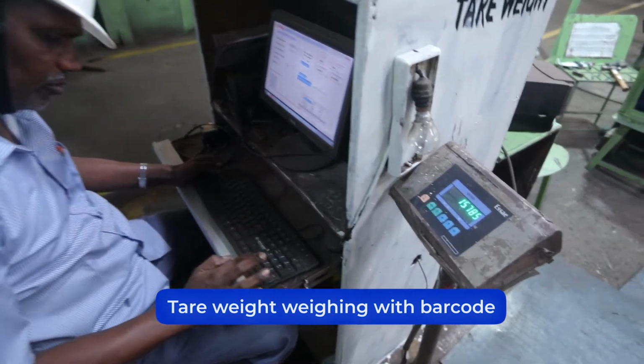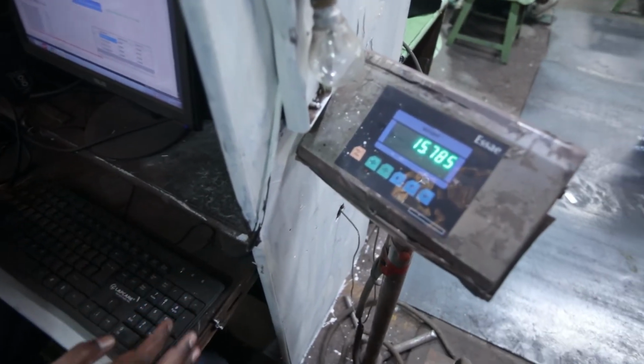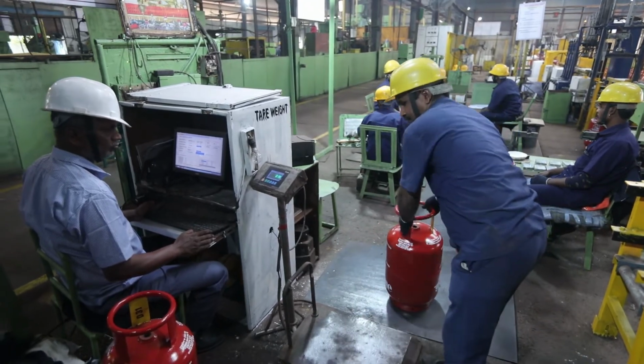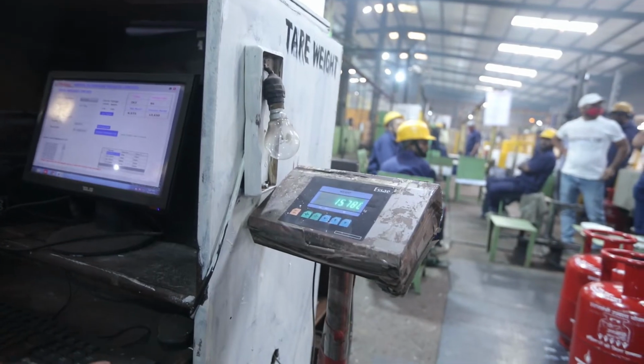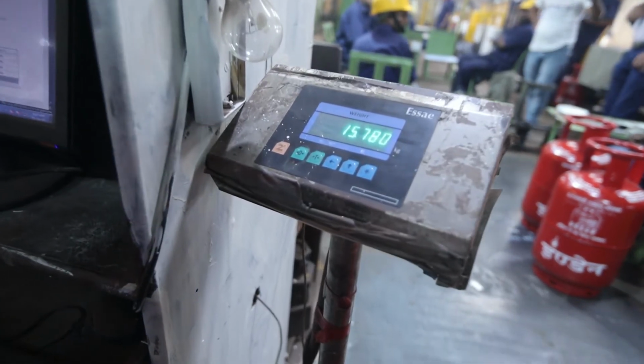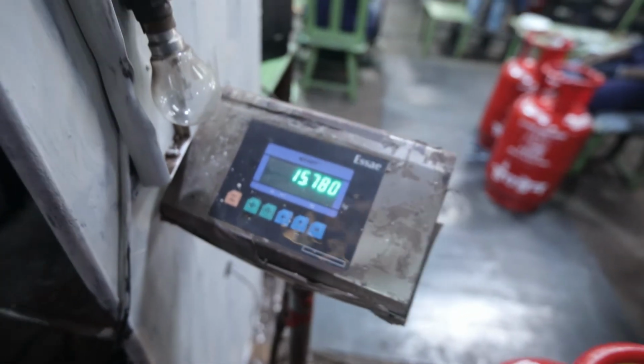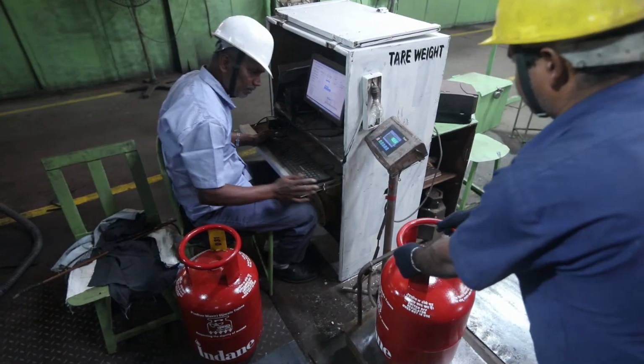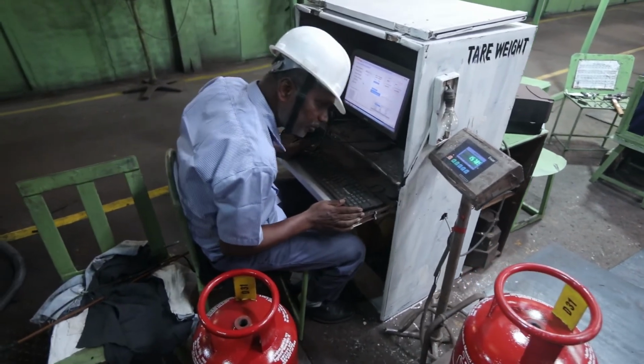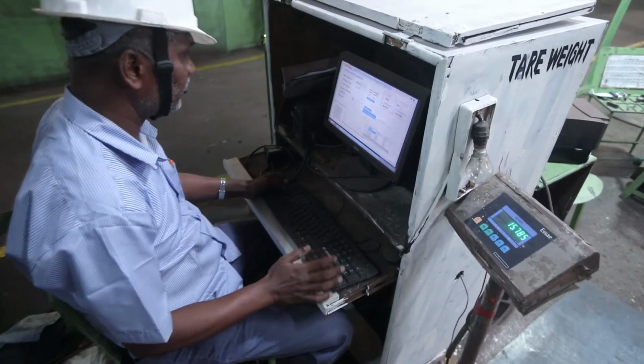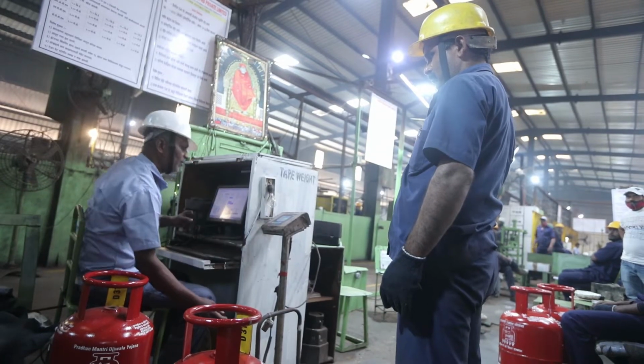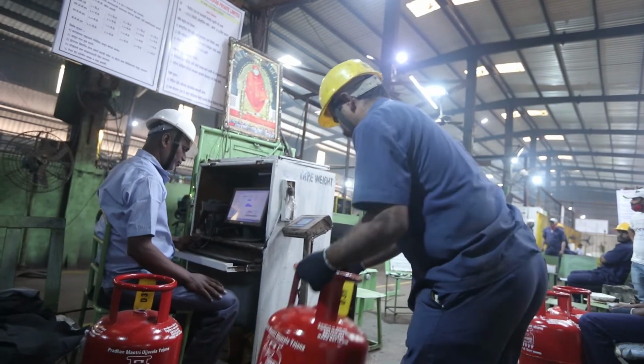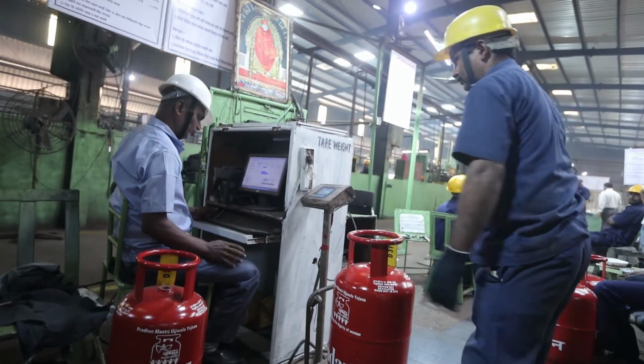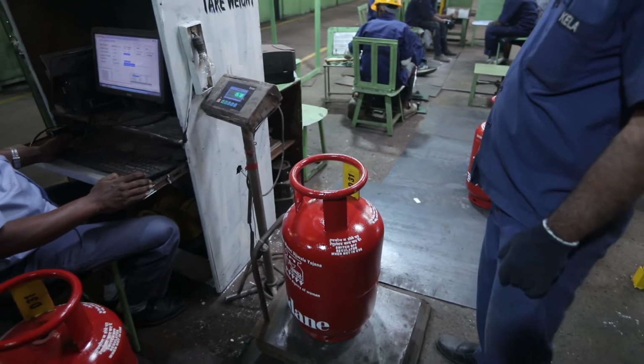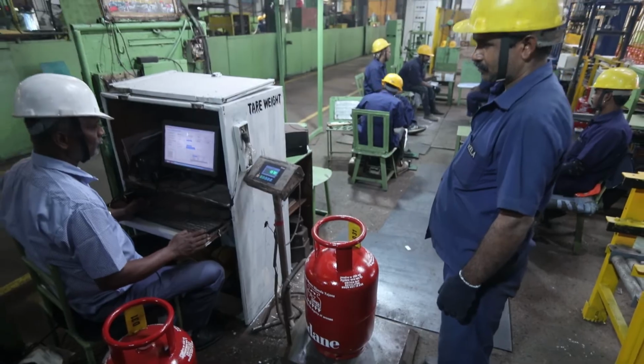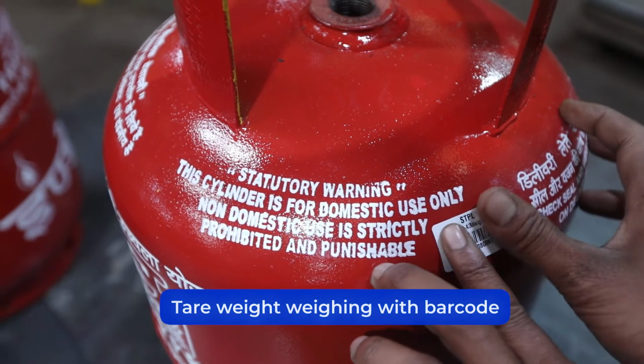To carry out the procedure of tare weight weighing with barcode, use an electronic weighing machine. The capacity should be 0 to 60 kg with a least count of 5 grams. It should be daily calibrated with 1 kg, 5 kg, 10 kg, 20 kg weights before weighing. The tare weights are rounded off as per the specification of IS2. Tare weight is measured along with SC valve and safety cap. Finally, batch-wise and serial number-wise, tare weight computerized barcode is generated.